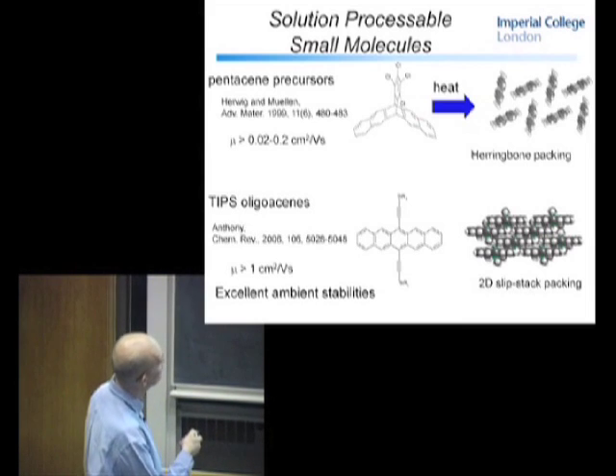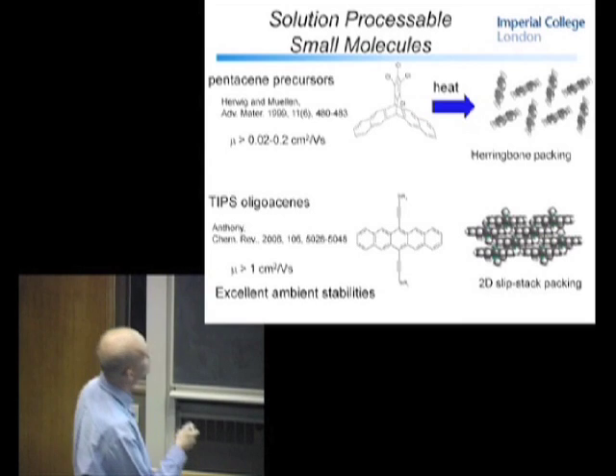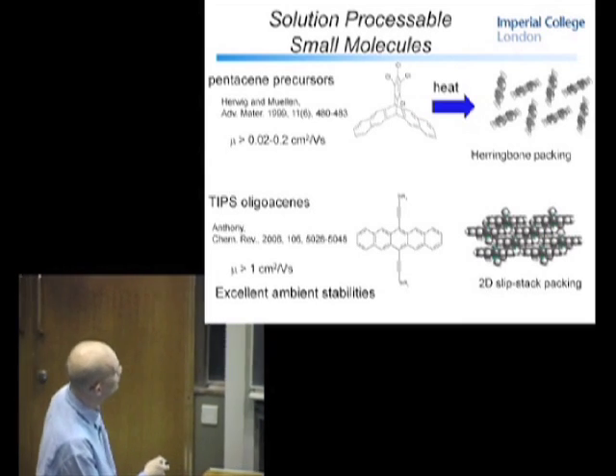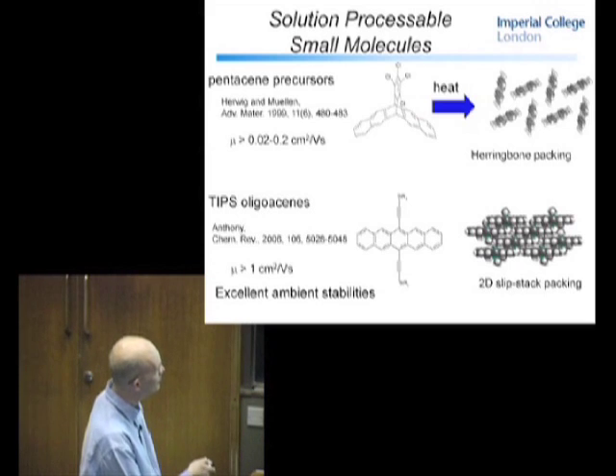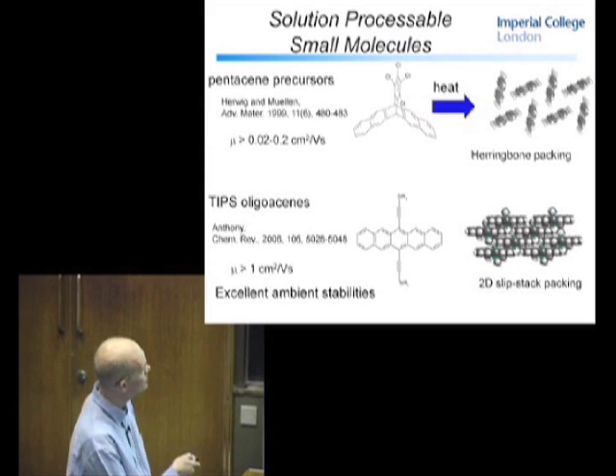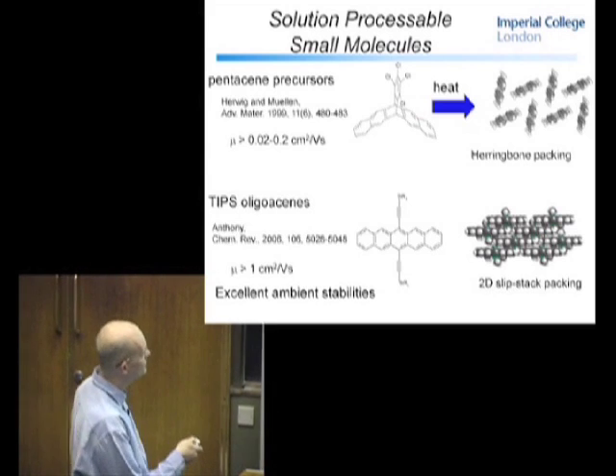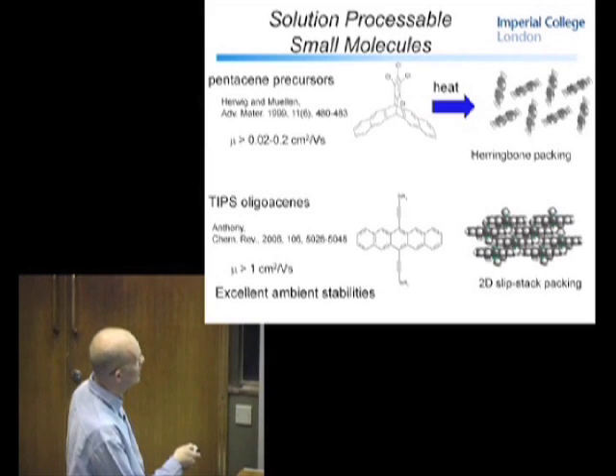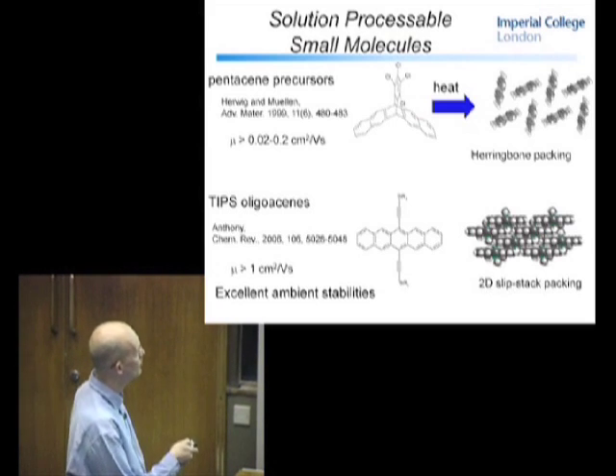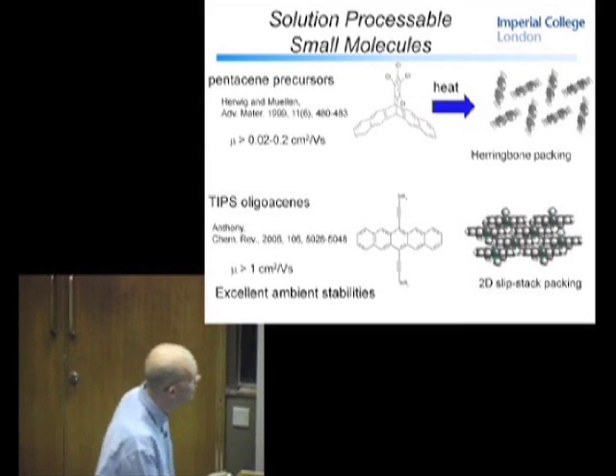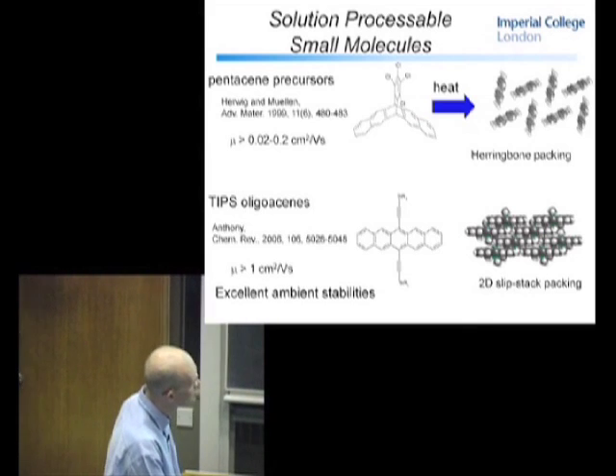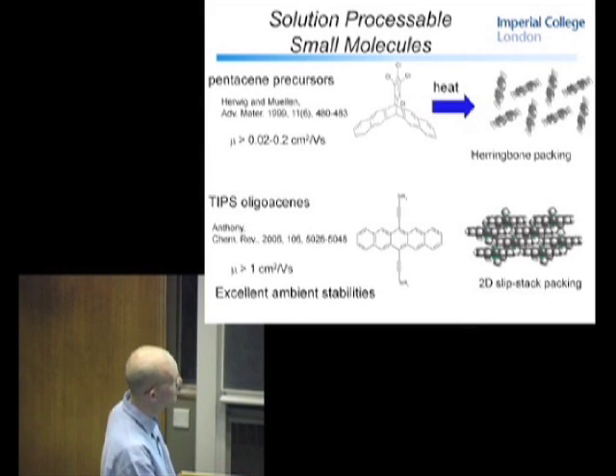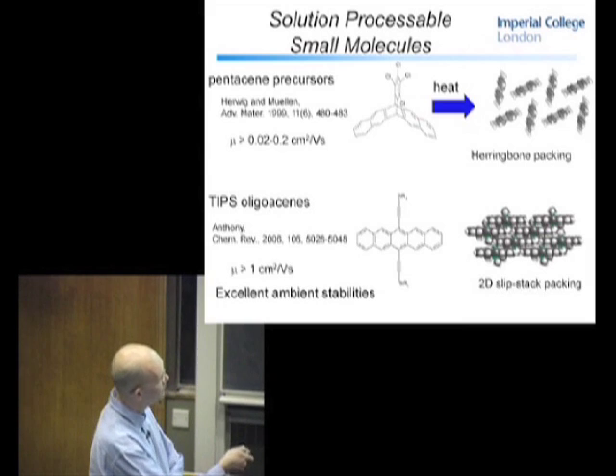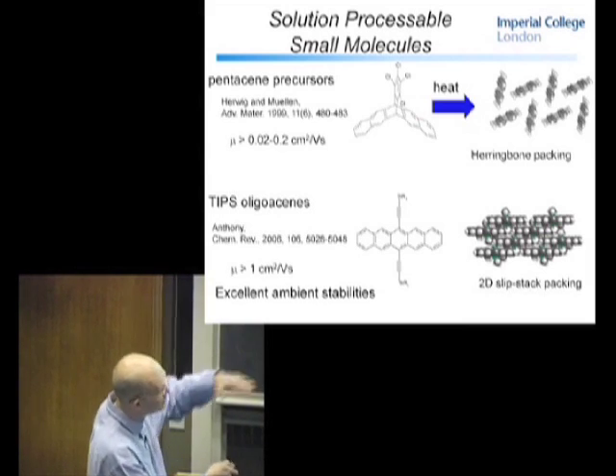Another way to prepare small molecule devices is to start off with, again, a soluble pentacene, but this time don't remove the precursor, just actually use it to prepare your crystal structure. What this is doing, you have these triisopropyl silyl acetylene groups in the 6,13 positions. And what they do is they force a 2D slip stack packing, where you get the face-to-face arrangement. So this is looking side on at these pentacene rings.